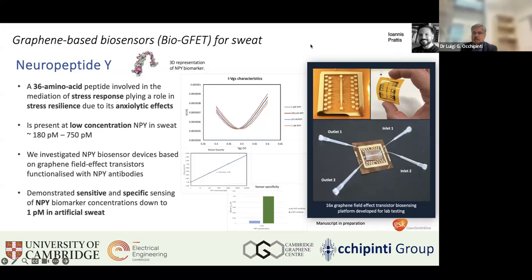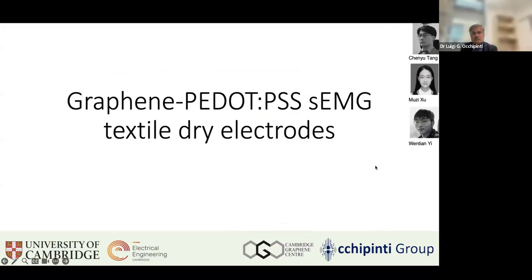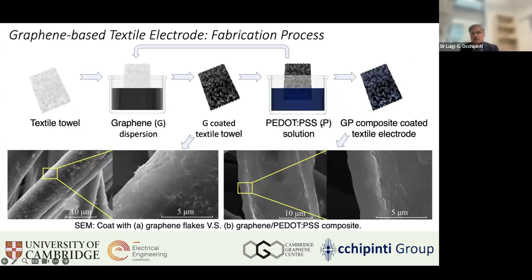And building upon other graphene-based sensors, I would like to quickly show you a few examples of graphene sensors for wearable devices. We also work on e-textiles and smart textiles. In this case, we use graphene combined with PEDOT:PSS as a conducting polymer for surface electromyography textile dry electrodes formation. The process is very simple. We started with a standard textile substrate. We used a dispersion of graphene, coated the textile electrode with the graphene ink, then introduced a PEDOT:PSS solution, and finally processed the textile for use as EMG electrodes.